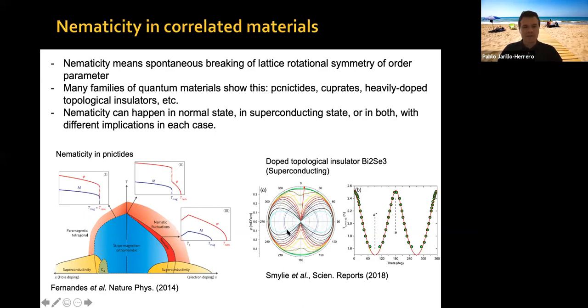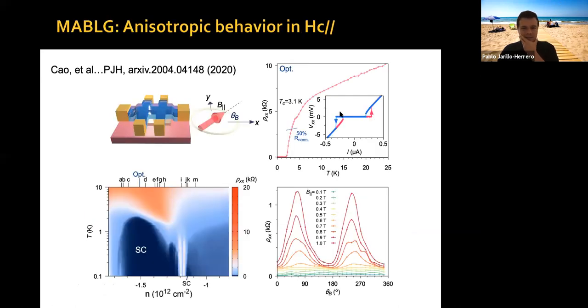So let me show you our results on magic angle graphene, okay? Again, this is a device that we have measured from many devices now. This is a device, you cool it down, it's a Hall bar geometry, and now you apply a magnetic field parallel to the device, okay, in plane, and you can vary the magnitude of the magnetic field as well as the angle of the magnetic field, yeah? And again, this is a pretty high TC device, 3 Kelvin, 50% of normal state resistance. Beautiful switching curves, they even have some hysteresis, okay? And by all standards, really a very high quality superconducting device.